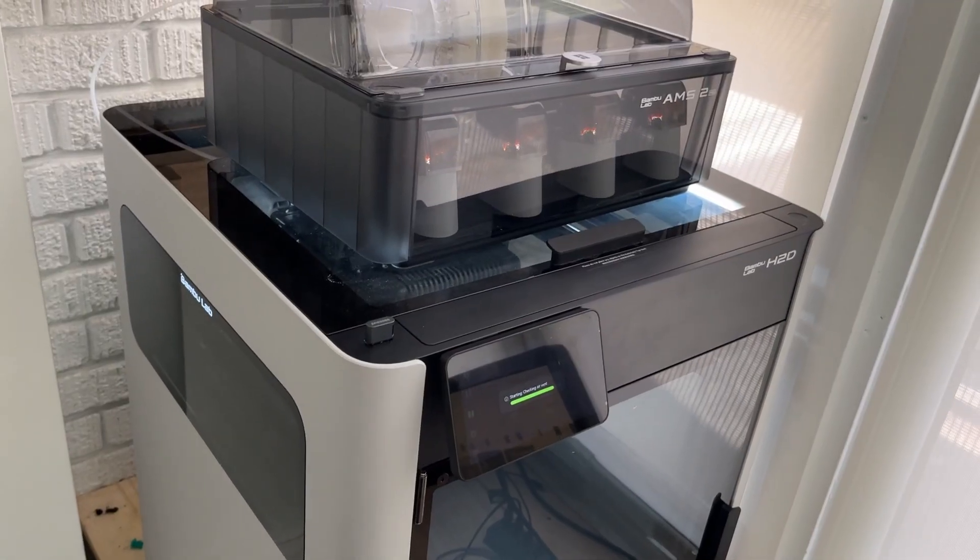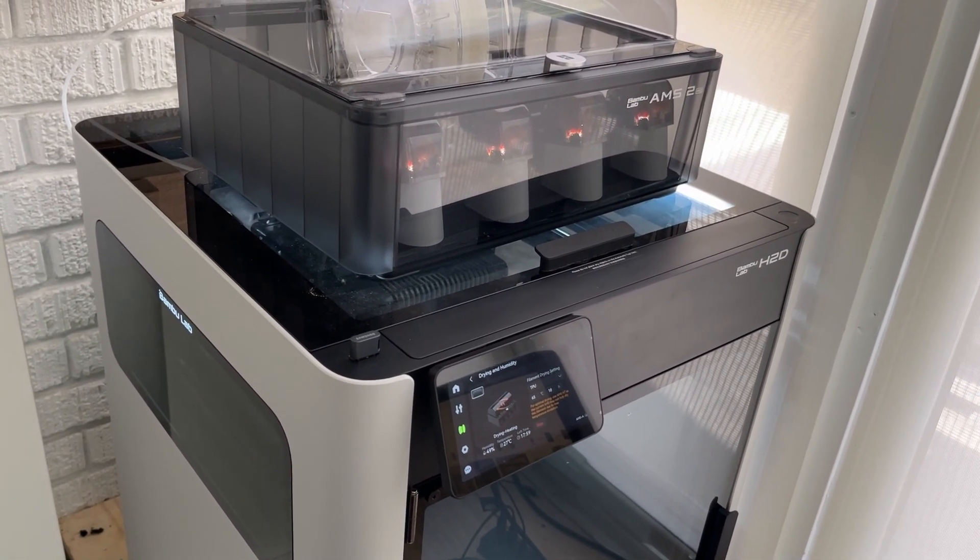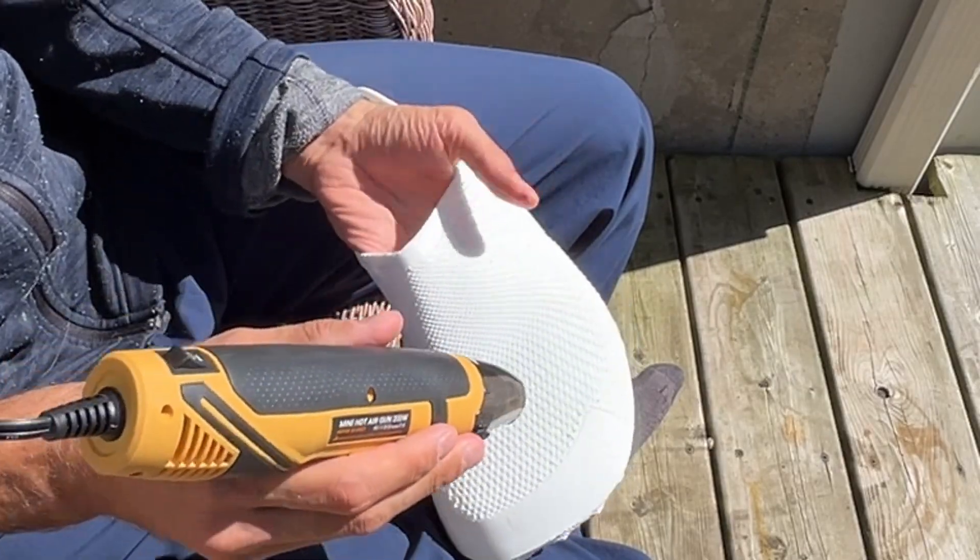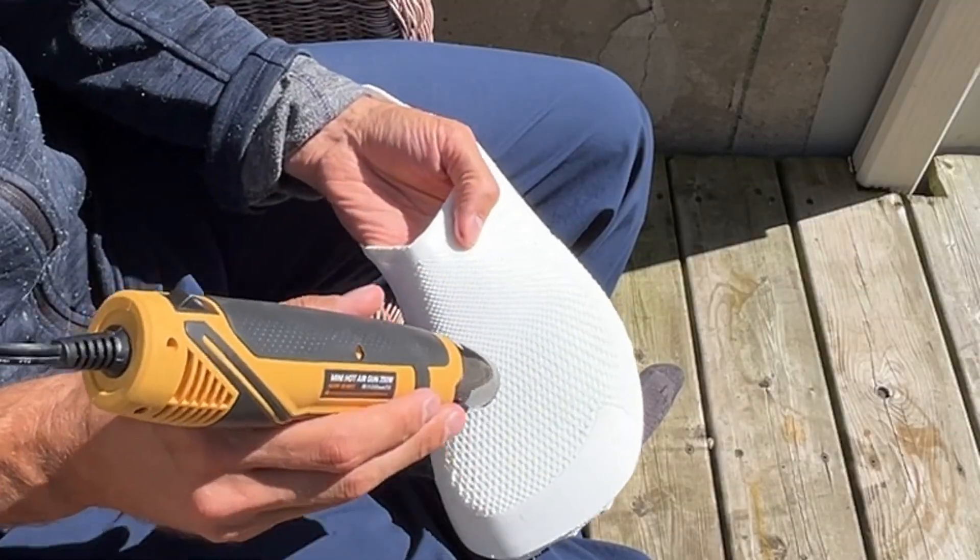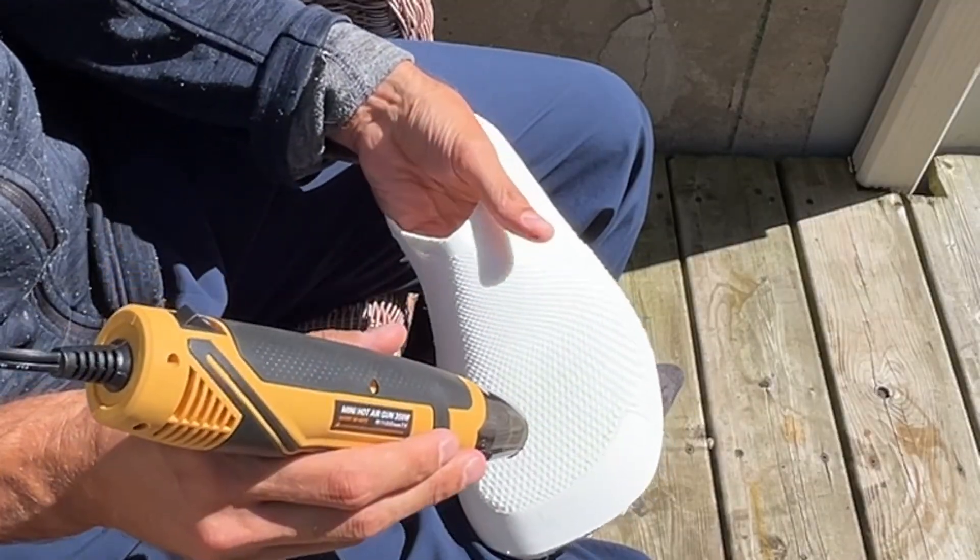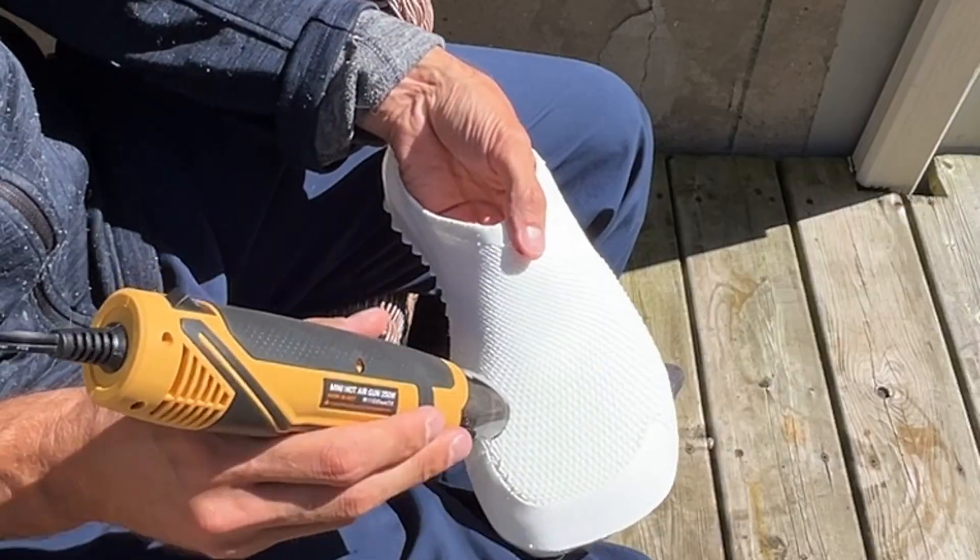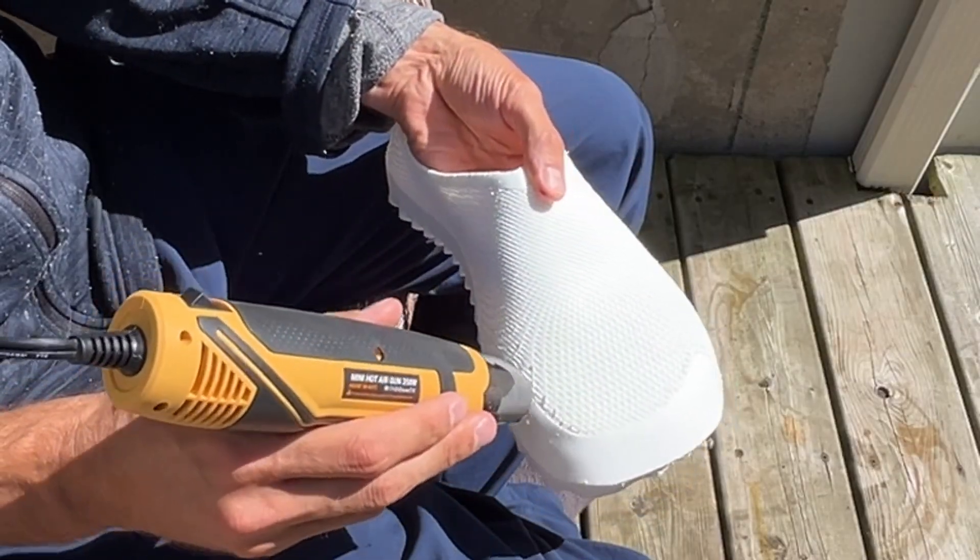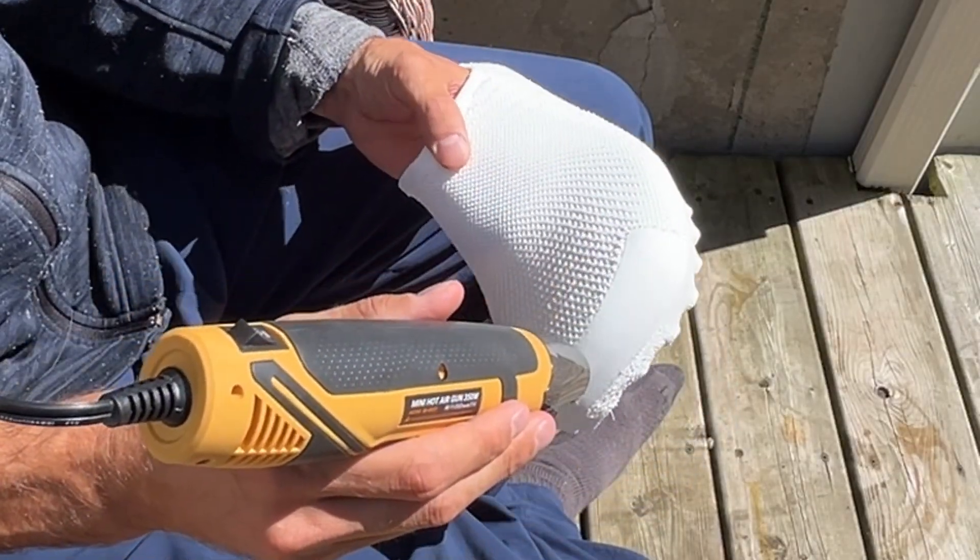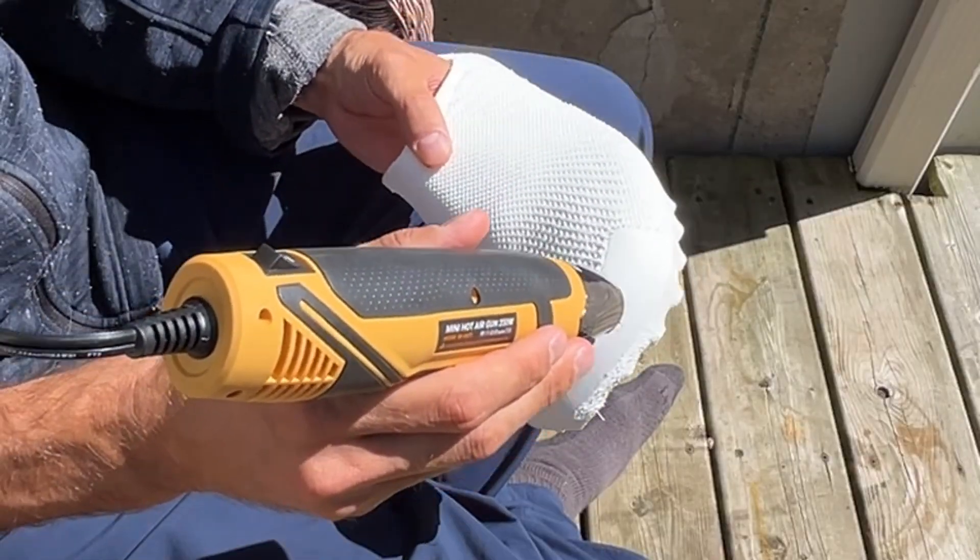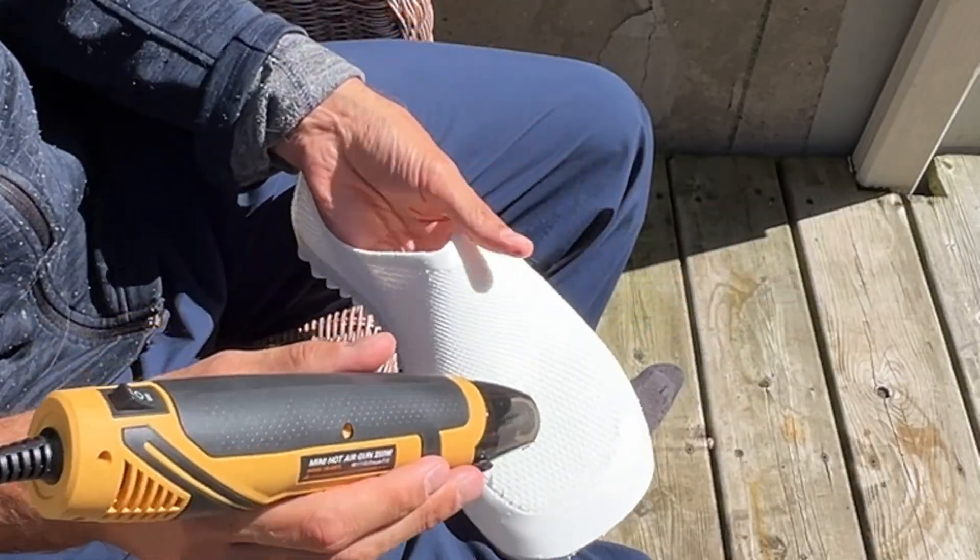On the other side of things, for post-processing, I found it helpful to re-melt, aka anneal the TPU to improve interlayer adhesion. Otherwise, the shoe is prone to tearing. I used a heat gun, though perhaps a carefully controlled convection oven could do it. By blowing hot air amongst the fine threads of the infilled upper, they melt very easily and bond together, allowing them to act more like an actual woven fabric.